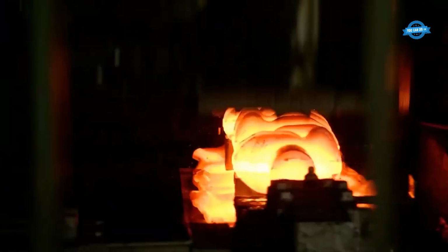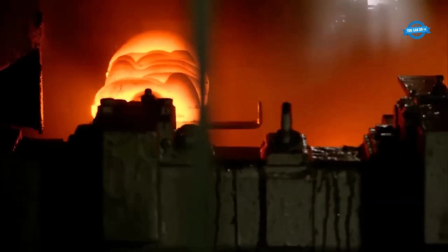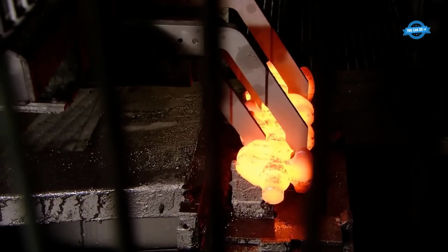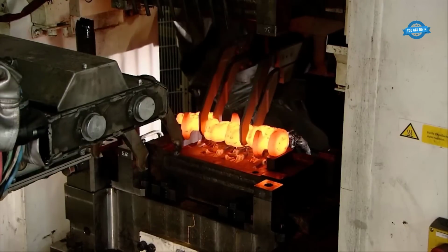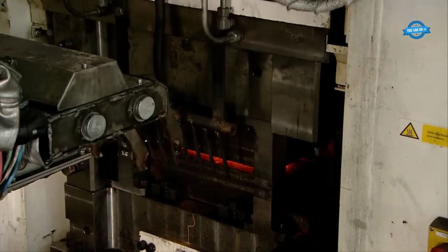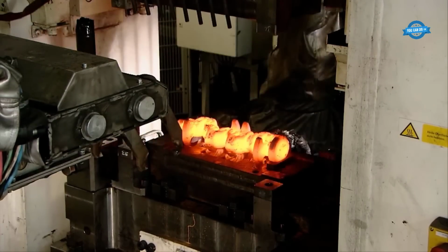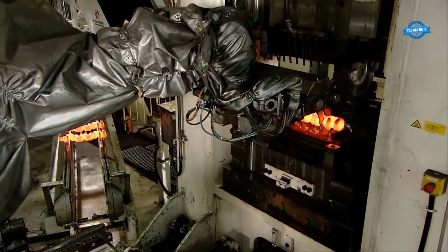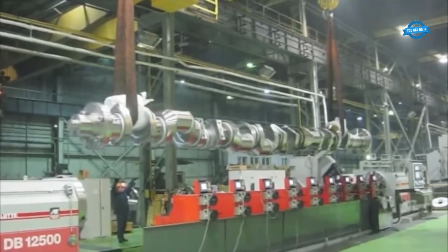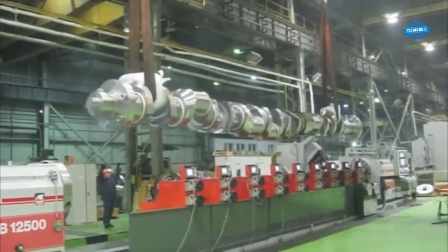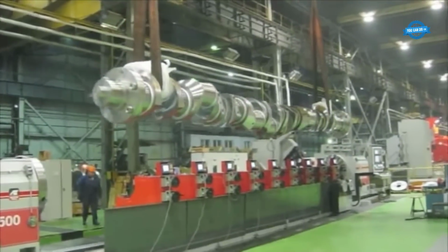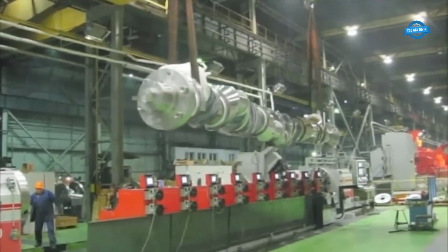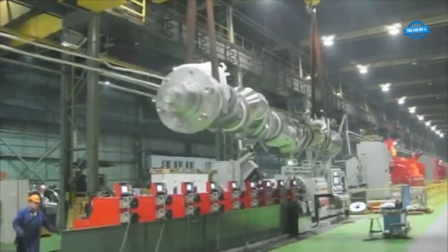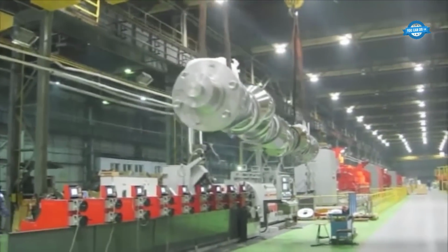A 2,500-ton hydraulic press trims and calibrates the shape, followed by controlled cooling to relieve stress. Modern facilities use automated warm straightening systems to correct heat treatments like induction hardening, achieving surface hardness up to 58 HRC, enhancing wear resistance. Advanced CNC grinding and superfinishing ensure surface roughness below Ra 0.2 micrometers. High-volume manufacturers produce up to 100,000 crankshafts annually, meeting the increasing demand for high-performance engines in commercial and industrial sectors.